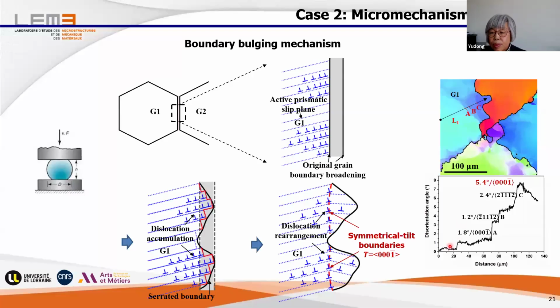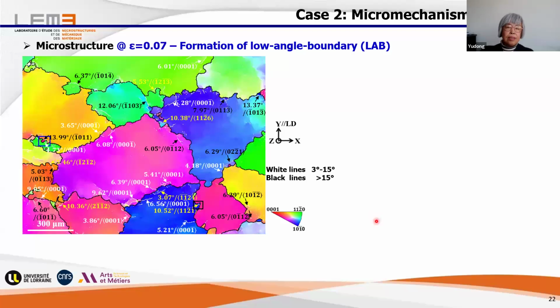If we plot the misorientation along this line, we see a jump, which is the formation of such a boundary. And so it's in place A, place B, place C. You see jump, plateau, jump, plateau, jump, plateau. And so this allows us to really clearly resolve how this bulging happened. Now we continue.